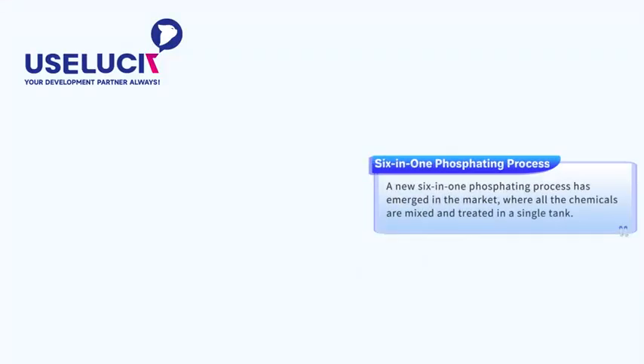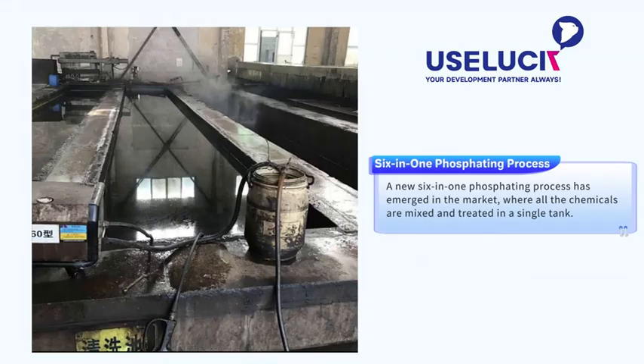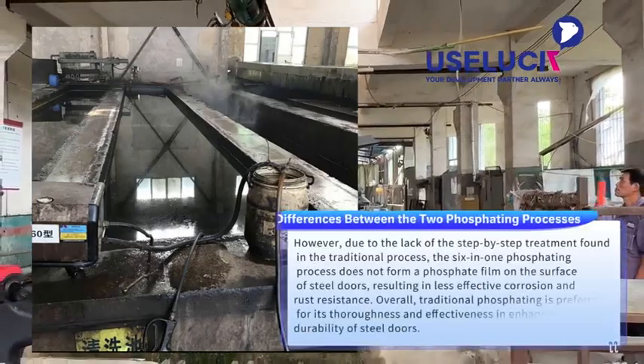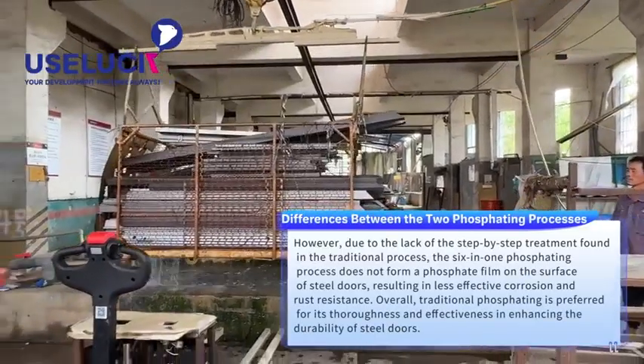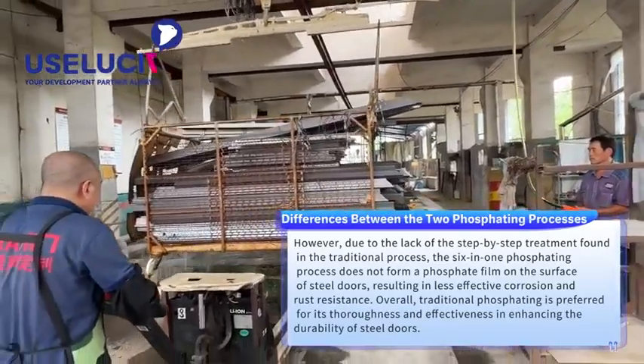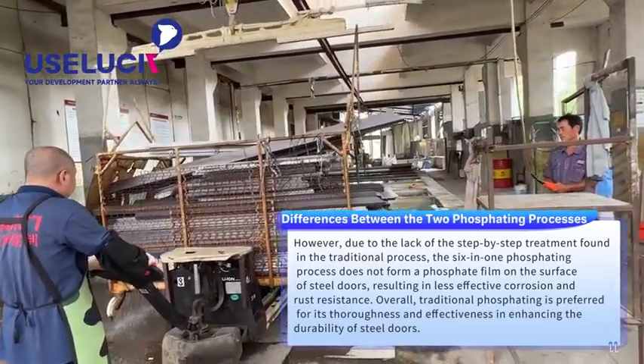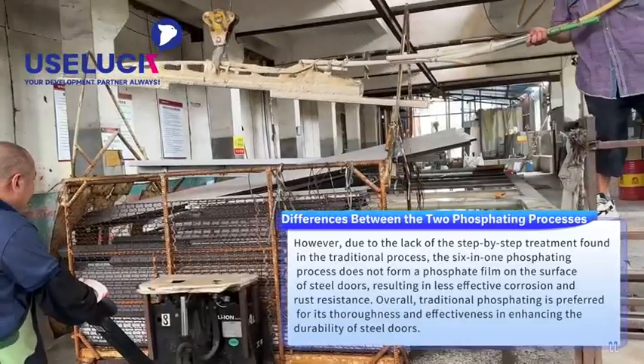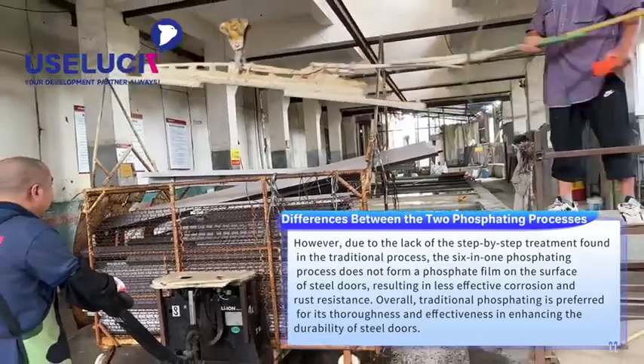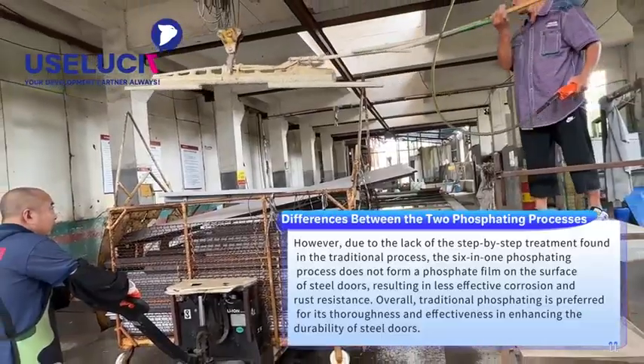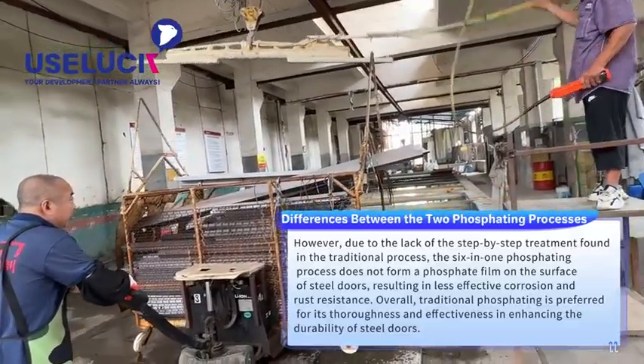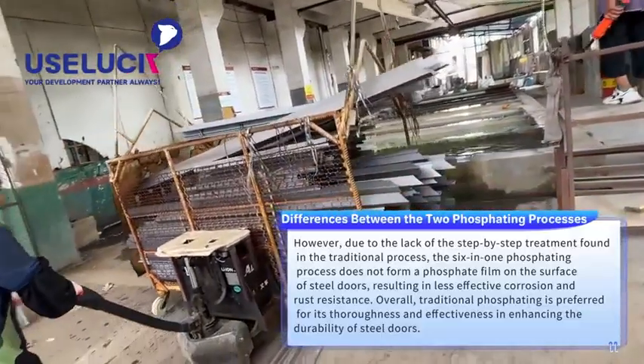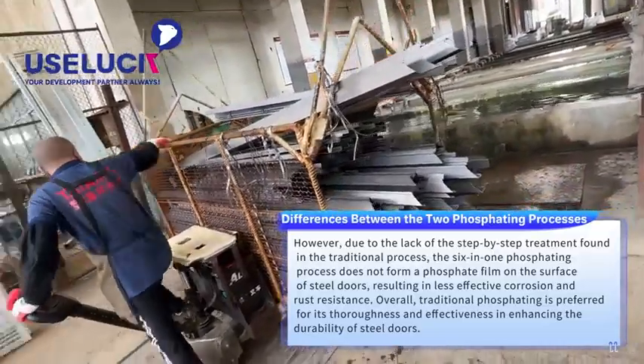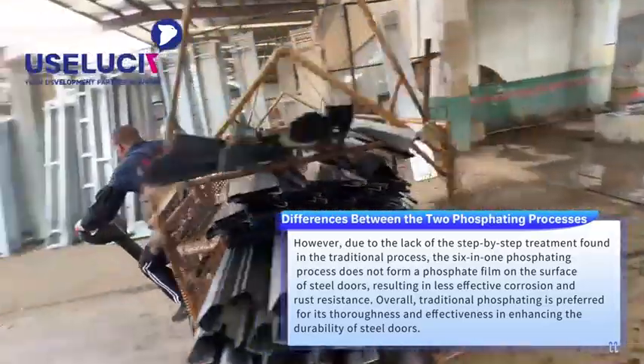6-in-1 phosphating process. A new 6-in-1 phosphating process has emerged in the market, where all the chemicals are mixed and treated in a single tank. Differences between the two phosphating processes: due to the lack of the step-by-step treatment found in the traditional process, the 6-in-1 phosphating process does not form a phosphate film on the surface of steel doors, resulting in less effective corrosion and rust resistance. Overall, traditional phosphating is preferred for its thoroughness and effectiveness in enhancing the durability of steel doors.